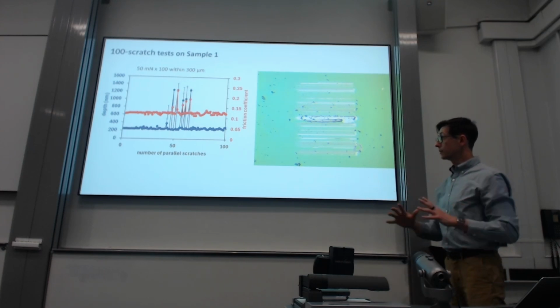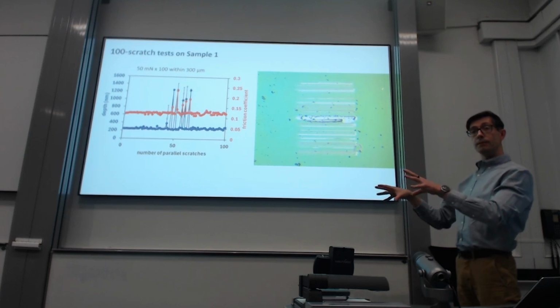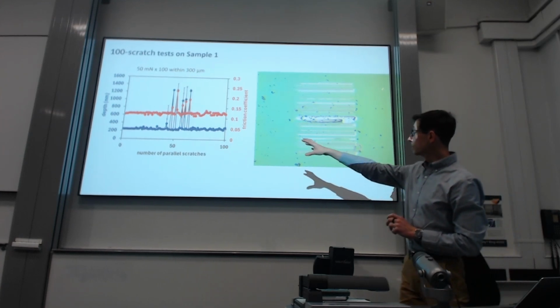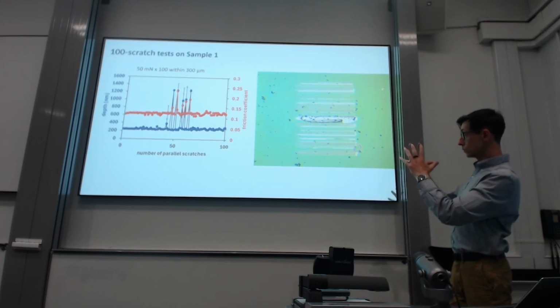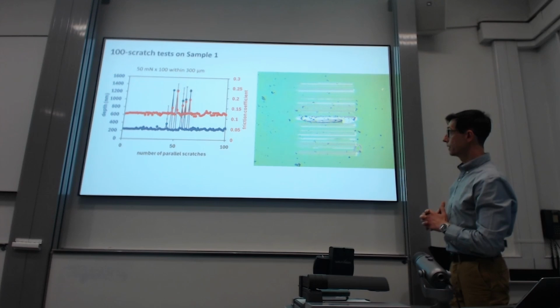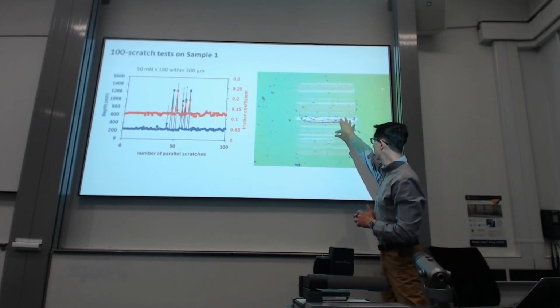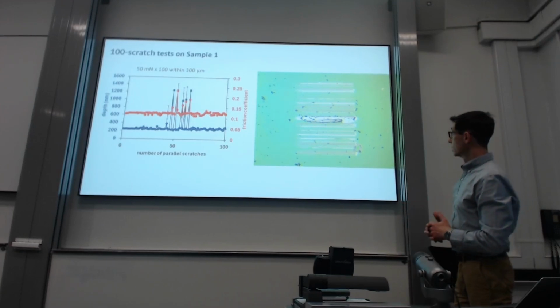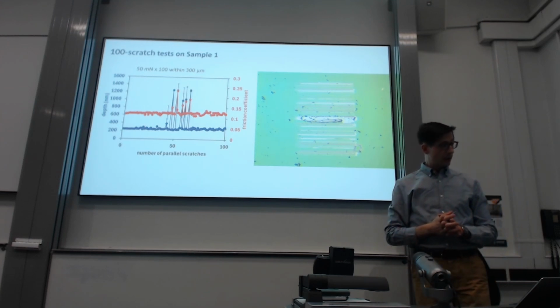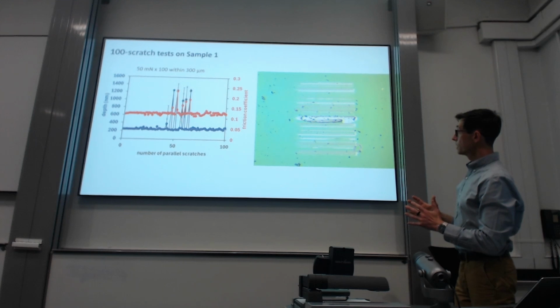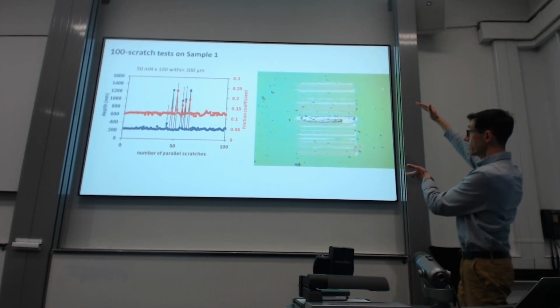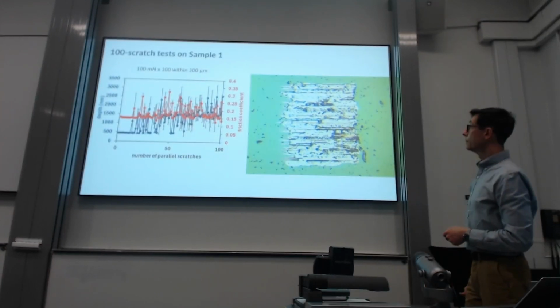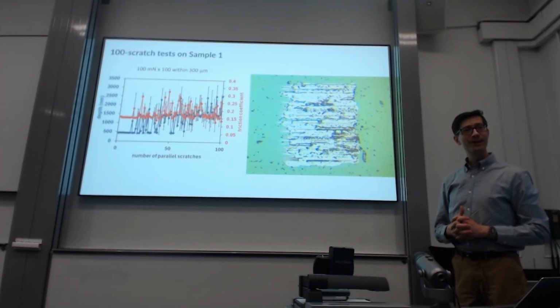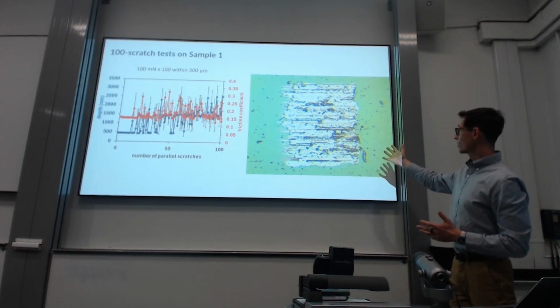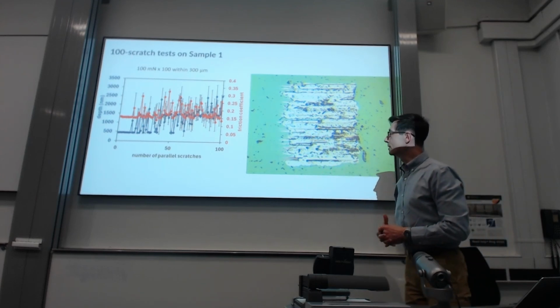Basically, we increased the area for the scratches to randomly appear in that space, and with that, you can clearly see much fewer events where you see an increase in depth and increase in friction. And of course, the part where you randomly generated more scratches generated some cracks, and that was clearly recorded in the depth and friction signal. In the last case, we decided to keep the same width, so 300 micrometers, but we increased the load to 100 millinewtons, and you can see that completely changed the picture, both in terms of the actual picture and also the depth and friction signal.